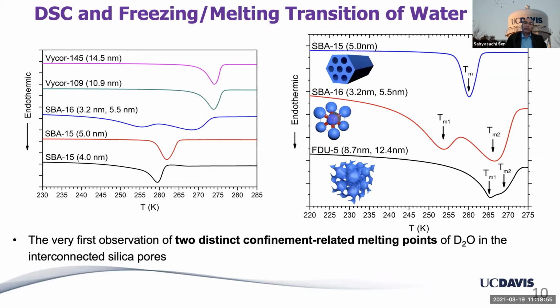And mind you, I forgot to mention that we are not looking at H2O, we are looking at D2O. The reason being we also want to do spectroscopy on them, and deuterium is one of the nice nuclei to do nuclear magnetic resonance or NMR spectroscopy, which is something that I like to try on different materials. So that's why we chose D2O. There's nothing different from H2O in it, except the melting point is around 4 degrees centigrade instead of 0 degrees for H2O.